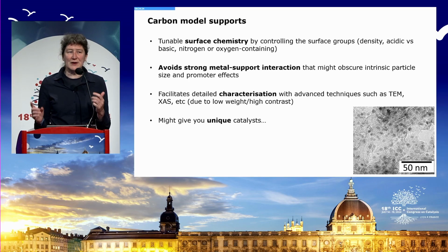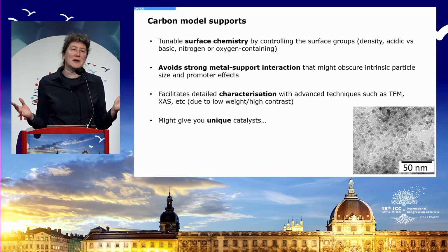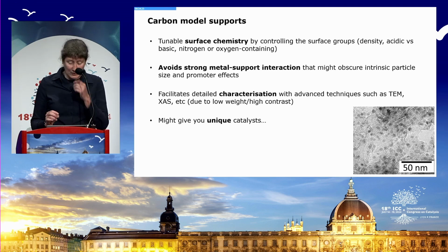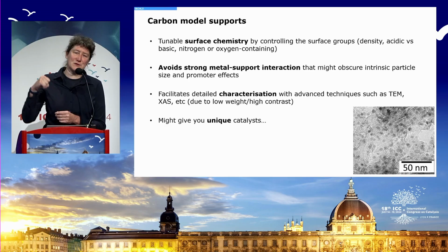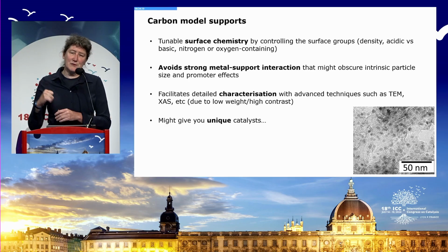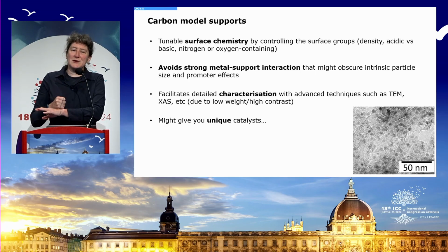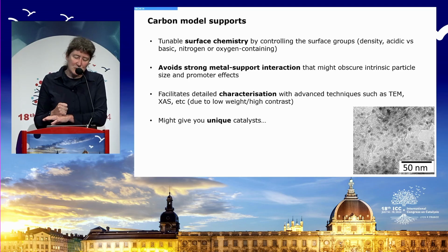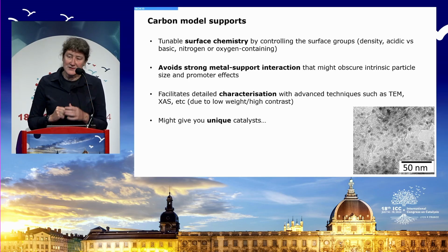While very often during reaction conditions, if they're a bit more harsh, your functional groups will actually be gone. So it's just to help the preparation as well. Another reason why I like them is that you really can look at particle size effects, and they're almost freestanding particles. They have a relatively weak interaction with the graphite support or carbon support or graphene support, which means that you can really study also intrinsic particle size effects.